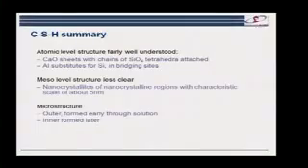And on the microstructure, we can see these very complex morphologies, particularly of this outer product with these fibrillar or filmy kind of structures. And this is the important part that's formed early through solution. And then this dense inner part, which in terms of transport properties is probably of less concern to us.